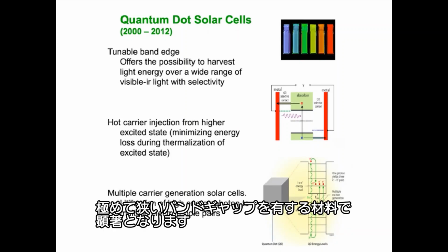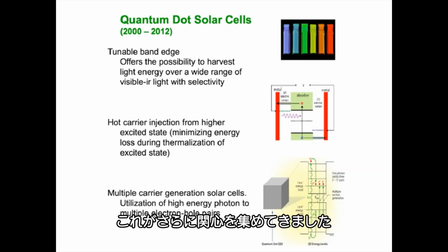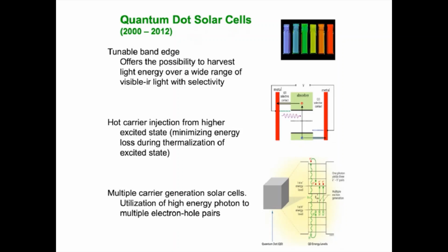And third, another interesting property is multiple carrier generation in solar cells, especially in systems such as lead sulfide, which is a very low band gap material. One can use high energy photons to generate more than two pairs of charge carriers per photon in this system. So this has gained much more attention, and let's see now how we make these quantum dot solar cells.